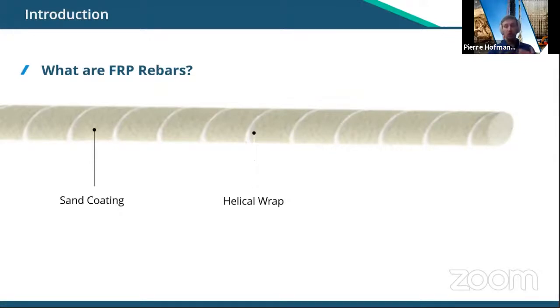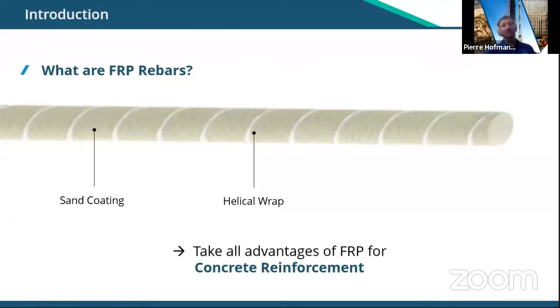So as per the code, we guarantee 9.6 MPa, making this much better than steel rebar, of course, than steel strand, or even fully threaded steel bar. All those products will have a lower bonding property than a GFRP bar. This is one of the advantage we find with a GFRP rebar.